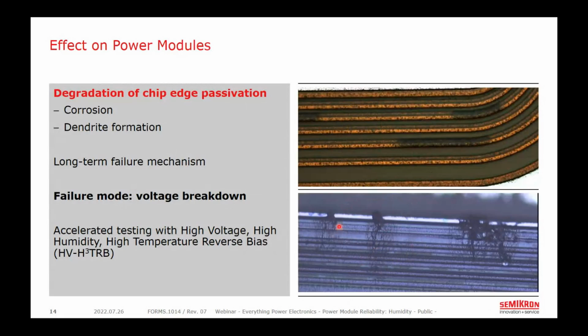And the end failure is a voltage breakdown from cathode to anode in the case of a diode, or from IGBT collector to emitter, and possibly the gate as well, since there may be a gate runner around the outside of the chip. What I want to point out here is that this is a long-term failure mechanism that can take months or years in the field depending on the level of humidity. So for evaluating the robustness of a module or chip against this failure type, we use accelerated testing.